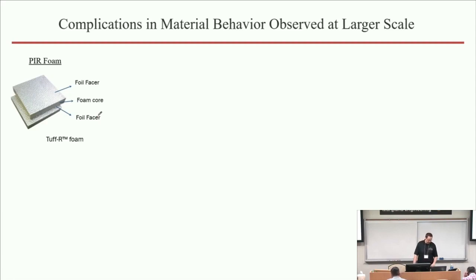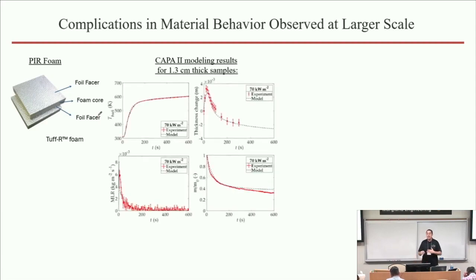and highly flammable combination. But here we focus on PIR foam, and we parameterize it based on the principle that I just outlined. So we went and measured kinetics, we measured thermodynamics, we looked at the CAPA data and made sure that our mass loss rates from these PIR tests were predicted well, and so on and so forth. And then we tried to actually make predictions of the behavior of this material, of its spread on a vertical wall, which was about 2 meters tall, and it was pure PIR panel.